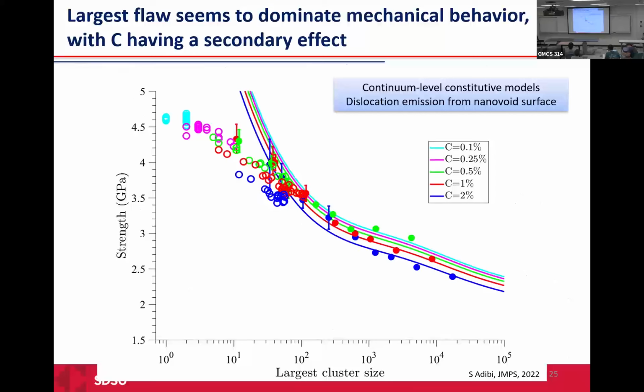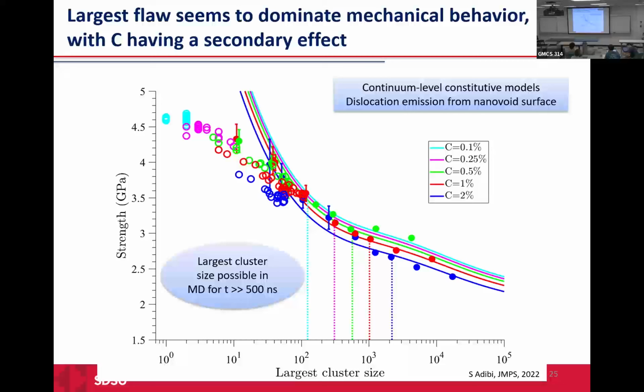This is the data from the continuum level model that we have generated based on the dislocation emission from nanovoid surface. And we are trying to use this data as well. You can see that there is a good balance between those continuum model results, except for the very small cluster size, and the one that we already have from MD simulation. And if we give enough time to the clustering process, it can give the same data that we have. Then the next step that we are doing is changing this part of the continuum model.